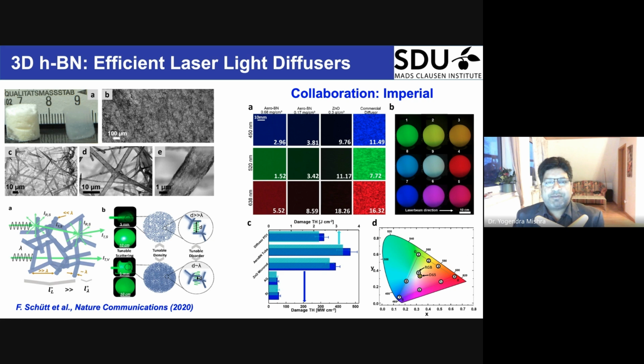Not just carbon nanotubes, we could even grow very tough materials like boron nitride. It is very difficult to grow boron nitride in simple conditions in a 3D network form, but using these templates in the CVD process in a simple VLS chamber with the help of ammonia and borax chemicals, we deposited boron nitride and removed the underneath zinc oxide, and such a boron nitride network was created. And we demonstrated this hexagonal boron nitride network as a light diffuser element.